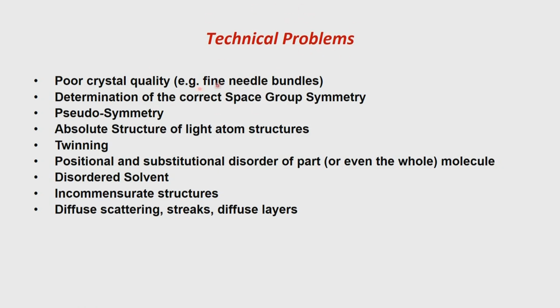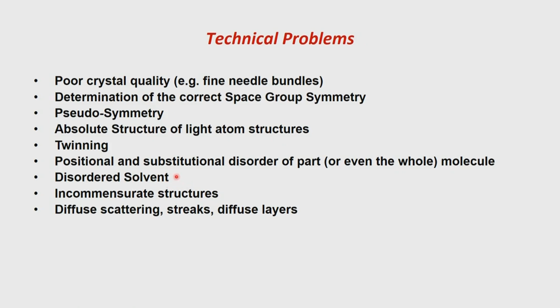The other technical problem we normally face, particularly in larger molecules, is the disordered solvent. The solvent may be fully disordered or partially disordered, because most protein crystals crystallize along with solvent water, and this solvent water has no structure of its own, it is disordered, and because of that we will get what is known as diffuse scattering. So, apart from the single crystal diffraction coming from the system, you will also have diffuse scattered radiation coming out of this disordered solvent, and as a result the actual evaluation of individual reflections coming from the crystal becomes an issue, and it is not going to be very easy.